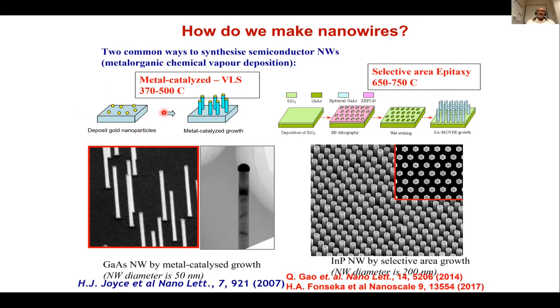So now if I introduce this gallium arsenide wafer with the gold nanoparticles into the MOCVD reactor, heat it up to somewhere between 370 to 500 degrees Celsius, and then introduce the gases needed for the growth of gallium arsenide, for example trimethyl gallium and arsine, they get incorporated, it gets supersaturated, and crystals start precipitating out. You can see the beautiful nanowires grown by my former student, who is now a professor at Cambridge University, Dr. Hannah Joyce, where she has demonstrated excellent atomically perfect nanowires.